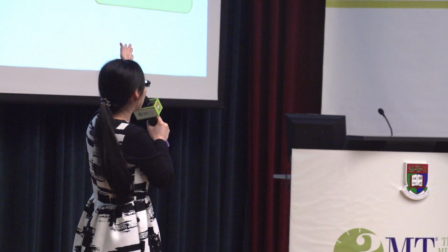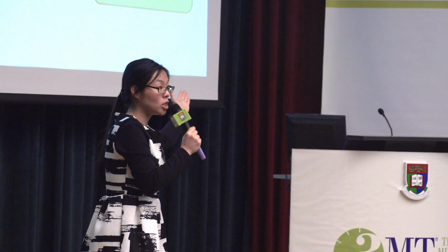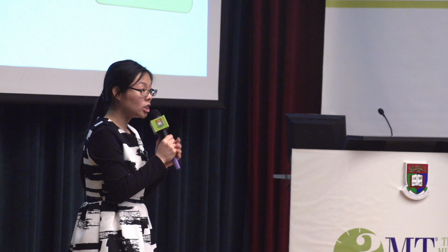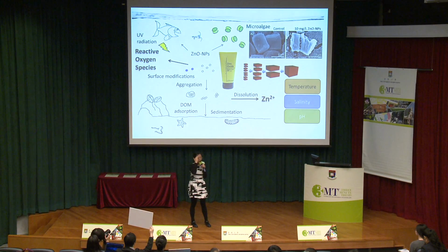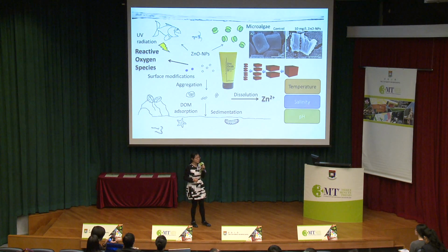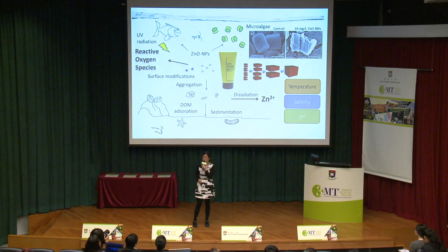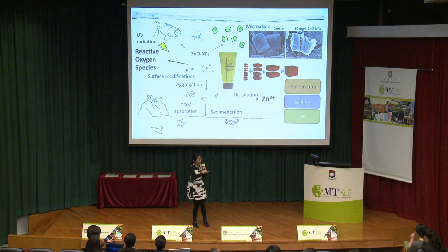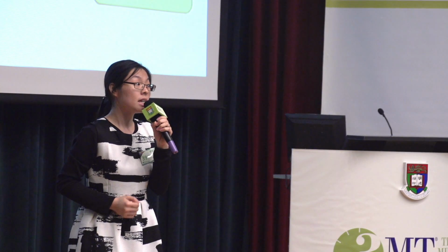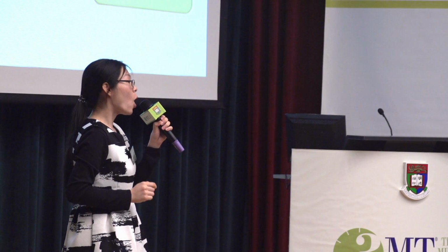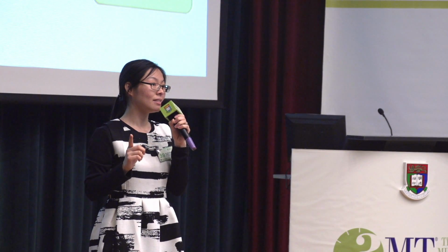Moreover, temperature, salinity, and pH of the seawater could also change the toxicities of the nanoparticles. By knowing their toxic mechanism, I think about how we can reduce the toxicities of zinc oxide nanoparticles in the environment. I found that zinc oxide nanoparticles with an organic carbon coating were less toxic than the bare zinc oxide nanoparticles. This helps the development of eco-friendly sunscreen.